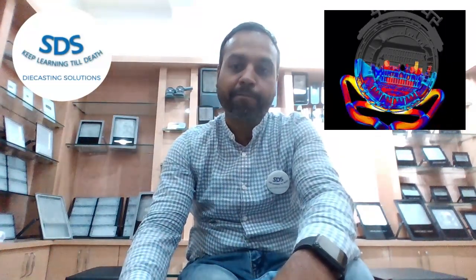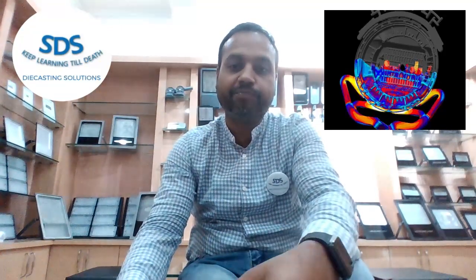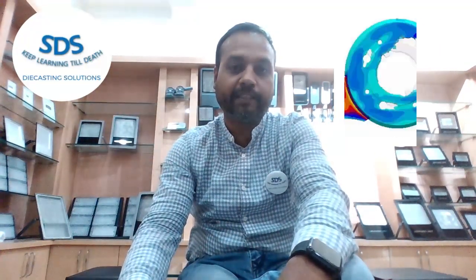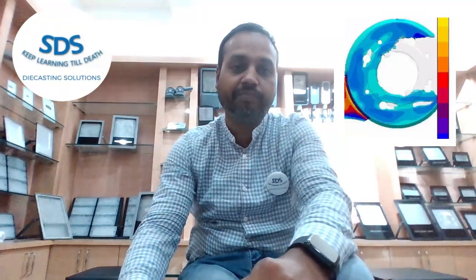A casting with an inconsistent wall thickness is more likely to trap air, and the molten metal will collect air as it flows through the die cavity. This air will become gas porosity if it is not washed out into the overflow. Another simulation shows the air trap in the metal flow, which will result in porosity. So we can control gas porosity with the die design. The die caster will engineer runner and vent design to minimize the amount of trapped air in the casting. Flow simulation, such as MagmaSoft or Flow-3D, must be used to optimize the runner and venting system for each casting. This simulation software allows casting engineers to model and test various ideas before the die is constructed.